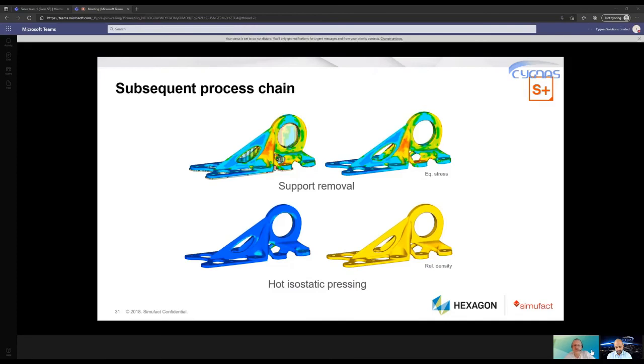Support removal can have an influence on your part. Not really on this one because it's quite stiff, but it can. And also, but that is more an aerospace application, maybe hot isostatic pressing has another influence on the distortion, on the stresses, and of course on the densification of the part. This can also be simulated.